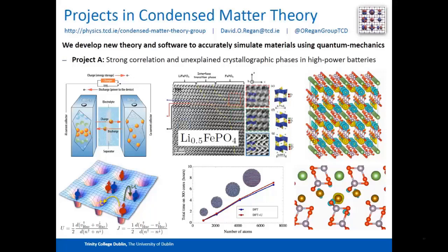And as a result of it, you get charge density waves and spin density waves. And when you look at your leaving cert chemistry, A-level chemistry, what you find in this half-charged state is every second iron atom, shown by blue and yellow here, is 2+ or 3+. But the state is degenerate. So there's no reason for one iron atom to be 3+ and the other to be 2+. So this, by construction, is a multi-state determinant wave function.